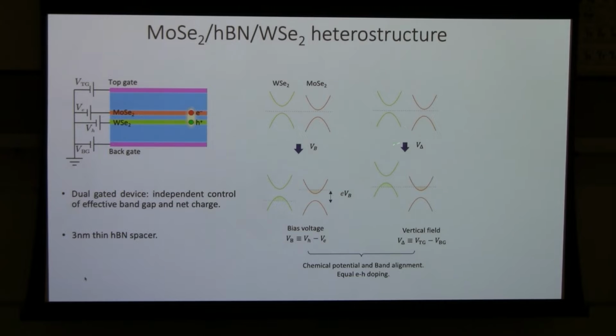Equivalently, we can use a vertical electrical field to reach the final goal. The idea is, if you apply a vertical electrical field, because the two layers are at different z positions, the potential energy will be shifted differently. As a result, the vertical electric field will shift down the conduction band relative to the valence band. If the field is large enough, we can shift the conduction band even below the valence band. Then, even at zero bias voltage, you can have holes doped in this layer and electrons doped in that layer. So these two knobs effectively do the same thing. They change the chemical potential and band alignment. As a result, they allow us to inject equal numbers of electron and hole doping in the system.